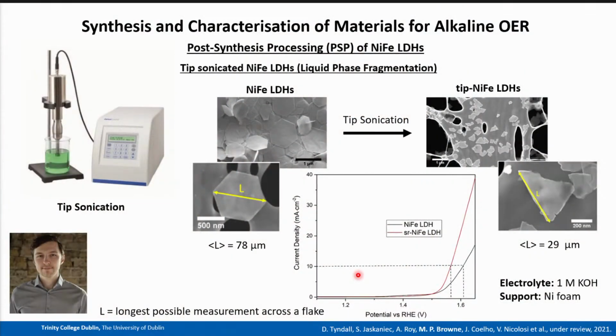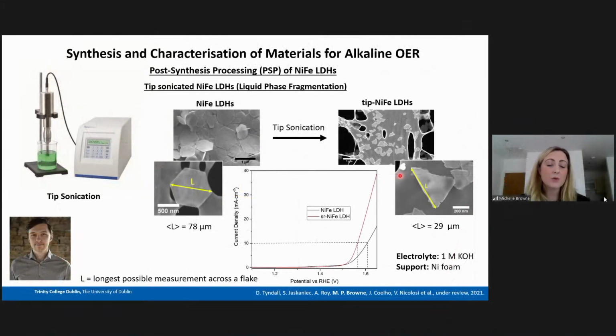And now we also wanted to look at the OER activity of these materials. So again, the same way as we prepared the as prepared material on the nickel foams, this was done exactly for the tip sonicated materials too. So first of all, in the black LSV, this is the as prepared materials in alkaline media. And then once we run the LSV of the tip sonicated nickel iron LDHs, we can see that there's a cathodic shift in the OER activity, which tells us that we are getting better OER activity. So this is super, but is there any way possible that we can perhaps enhance on this?